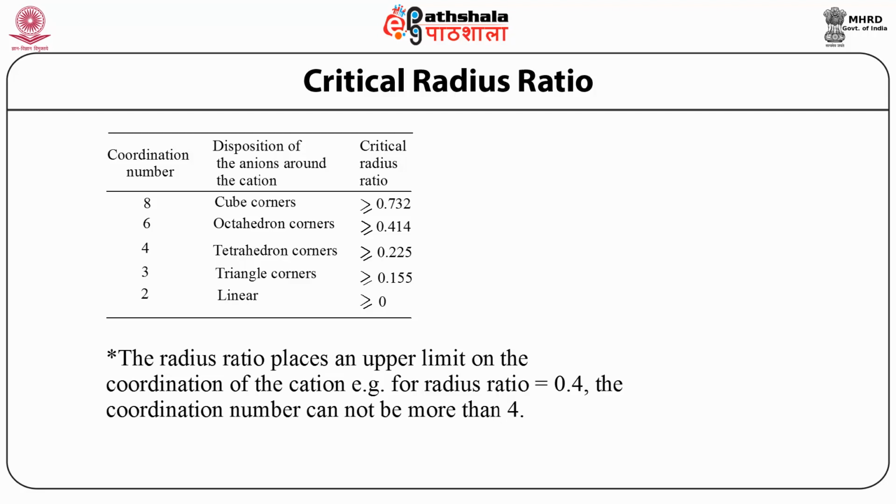In this case, for the ions to touch the central cation, some deformation of the ions will be necessary. This would increase the energy of the configuration. However, if the cation is highly charged, then the reduction in the electrostatic energy due to the increased number of anions surrounding the cation may be sufficient to compensate for this increase in energy.